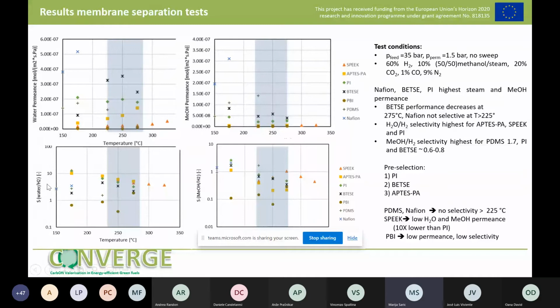If you look at the steam to hydrogen selectivity, the highest steam to hydrogen selectivity was with the APTES-PA membranes, which are the yellow squares, followed by PI and SPEEK. Based on this trade-off between the permeance and permselectivity, we selected PI membranes as the first preferred candidate, and also BETSE and APTES-PA as fallback options for further testing in membrane reactor conditions. The PDMS membrane and Nafion were discarded because there was no selectivity at temperatures higher than 225 degrees. And the SPEEK membrane, although it has higher selectivity, the permeance was 10 times lower compared to PI. And for PBI, we observe both low permeance and low selectivity.